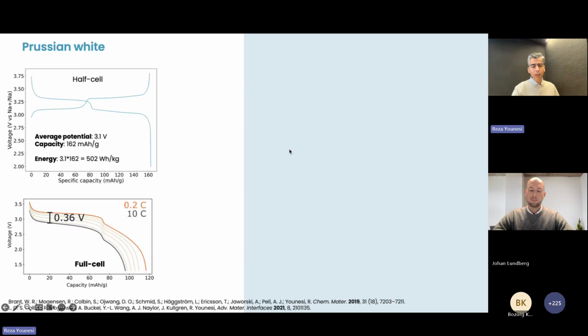The next and last example is Prussian white, which is the core business of Altris. The reason that we were interested in this material back in 2015, with my former PhD student Ronnie Mogensen and colleague William Brant, was that it's an interesting material in terms of capacity and voltage, but also you get two flat plateaus, kind of similar to LFP. So we were thinking to use this material as a stable counter electrode or a stable reference electrode when we study SEI dissolution. So we never aimed to commercialize this material, but we started to see how we could synthesize it in the lab to use it for other studies.